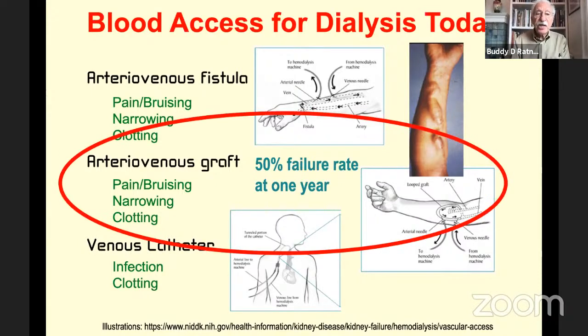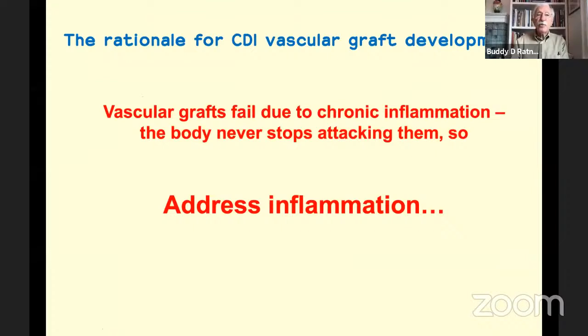We're going to talk about the central one, which is an arteriovenous, an AV graft. And the 2 needles are stuck into the synthetic graft between the artery and the vein. These have a 50% failure rate at 1 year, huge failure rate. And as you can see from the image of the arm, due to the needle sticks, they're quite disfiguring to the arms also.